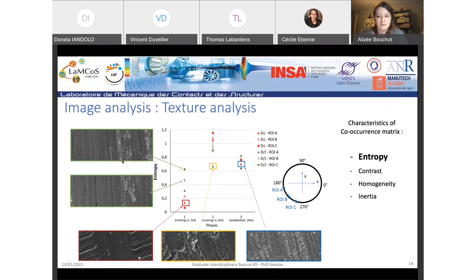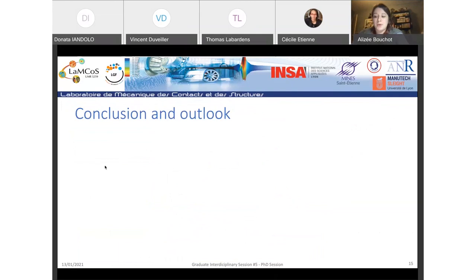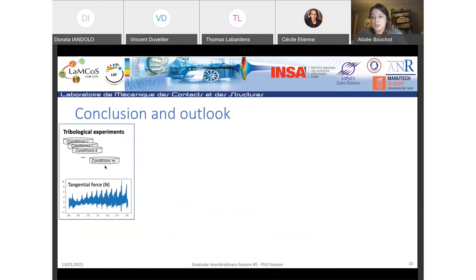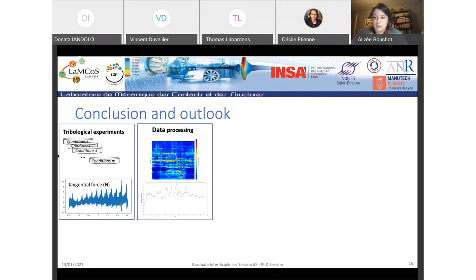So if we summarize the approach, several experiments are carried out under different conditions, ranging from the change of speed to changing the atmosphere in which the mechanism is located. This gives us different conditions with different data. It's then necessary to analyze this data. It makes it possible to know the evolution of contact, but also to locate where events occur, potentially accessible during the acquisition of images.